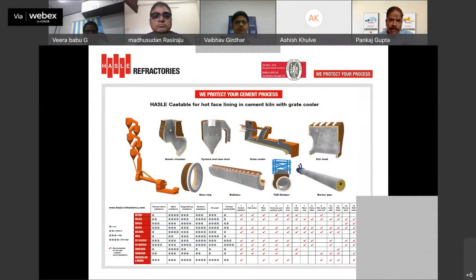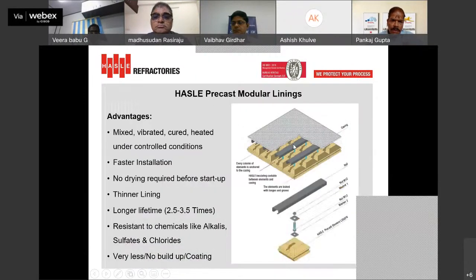HASLE produces refractory for most of the critical areas of the cement plant, whether it's the burner pipe, tip casting, bull nose, cyclones, smoke chamber area, or cooler parts. We have a very unique refractory solution that is universally known as modular lining. Its main advantages are that it is mixed, vibrated, cured, and heated under controlled conditions in our factory. It can be installed faster than low cement castable.